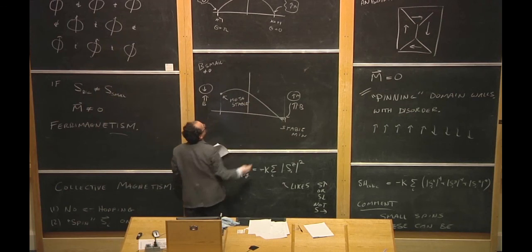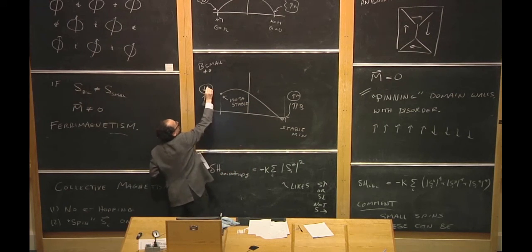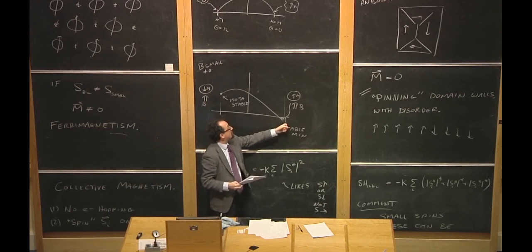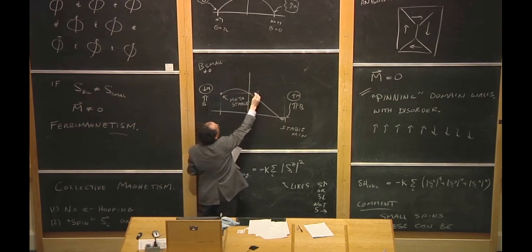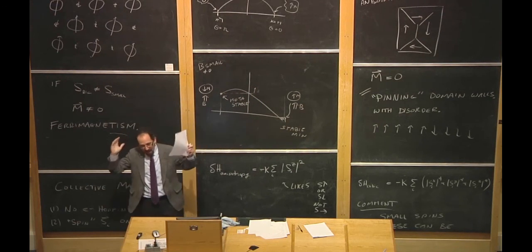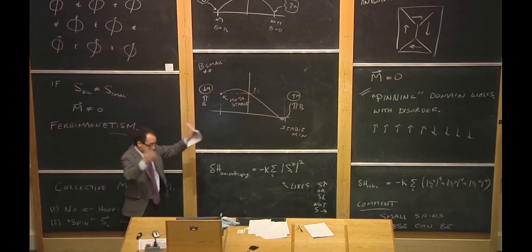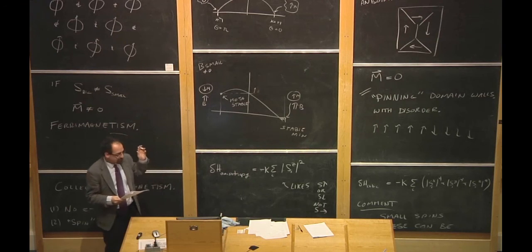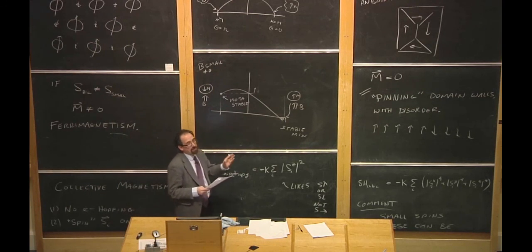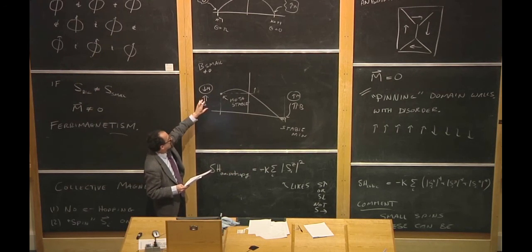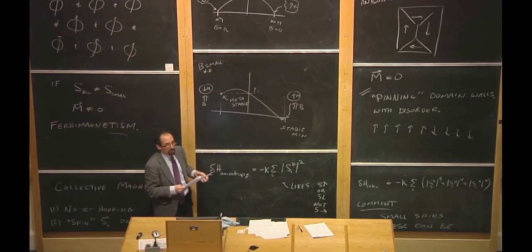In order to get from the metastable case of the magnetization pointing in the opposite direction as the magnetic field, down to here where it would rather be, it has to get over this activation barrier. And this means you have to take all of your atoms, maybe a million of these atoms, and somehow flip them all over simultaneously, either thermally or by quantum tunneling. And that's a process that's so difficult that at low temperature it may never happen. So you can have these little crystals of magnet have their magnetization stuck in the wrong direction.